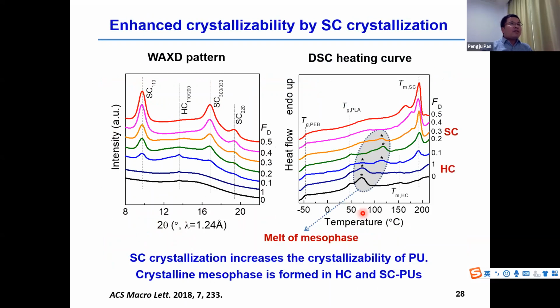X-ray diffraction results also confirm the polyurethane changes from a non-crystalline structure to a crystalline structure through stereocomplex crystallization. And we also found the polyurethane elastomer shows interesting thermal transition behavior in the DSC curve.